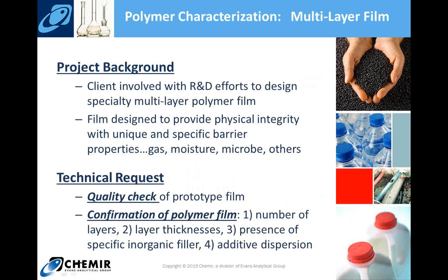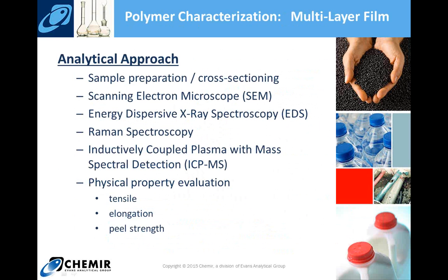Some of the things we were investigating were confirmation of the number of different layers, the layer thicknesses, which was very key to the performance, and the presence of some specific inorganic fillers and additives that gave the material some specific barrier properties. We also looked at dispersion of some of the additives, which is very key when you're formulating a polymer. You want to have your additives well dispersed. So that's what the client approached us with, a very challenging analytical task.